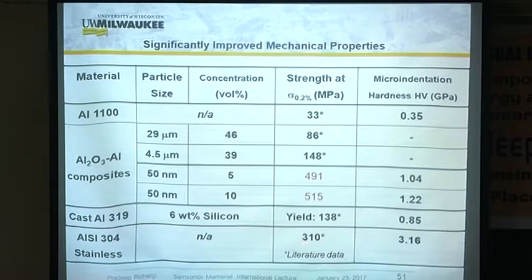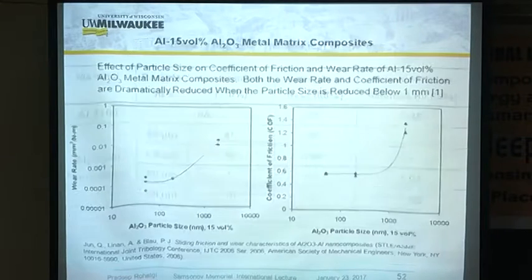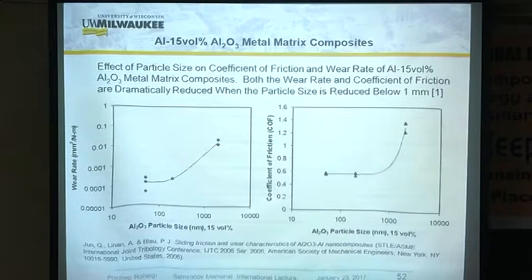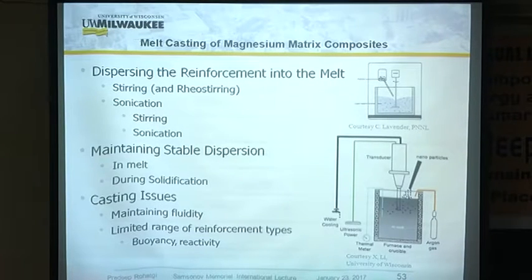It is more than that of steel. So for the density of aluminum, you can get the strength equal to that of steel. So that is what you can get in nanocomposites. Even the friction coefficient in nanocomposite is much lower, the wear rate is much lower. So not only advantages in mechanical strength properties, but also in other properties. The way to make nanocomposites is same.